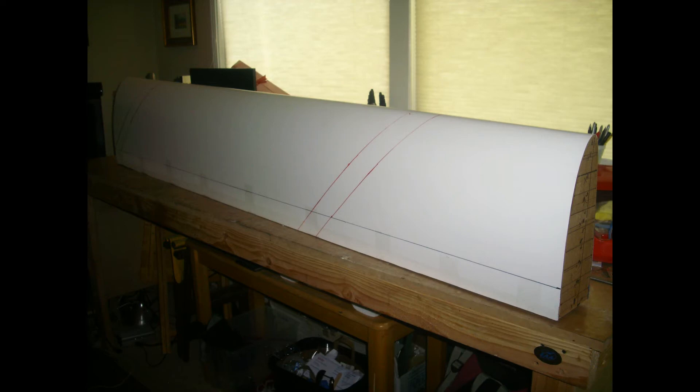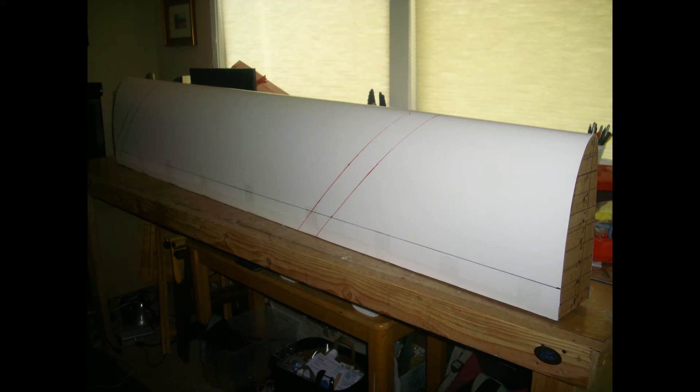Finally, you may wish to note the marks on the mold. These marks are on the 45 degree bias and are placed to represent where the carbon fiber cloth will be applied. One mark is at the end of where the cloth will lie, and the second is 2 inches inboard to represent the amount of overlap that is needed from one piece of cloth to the next. By laying the carbon fiber cloth on the bias, the tows that make up the fabric are aligned with the torsional load in the wing, and thereby are able to help carry a higher load.